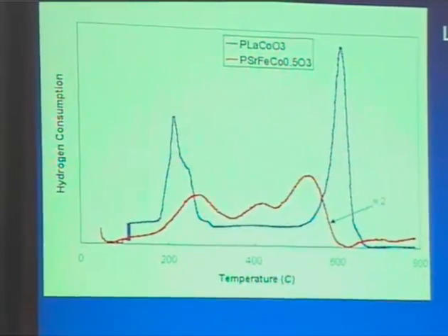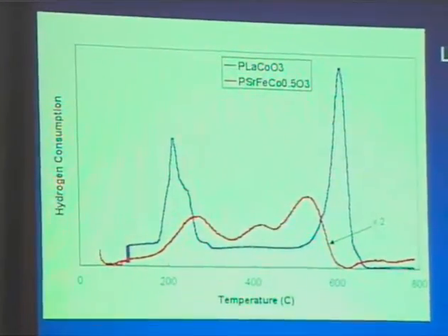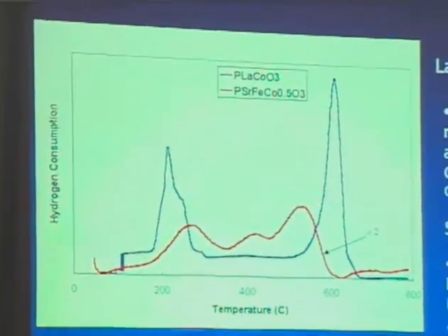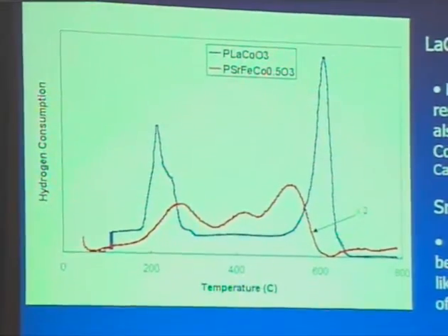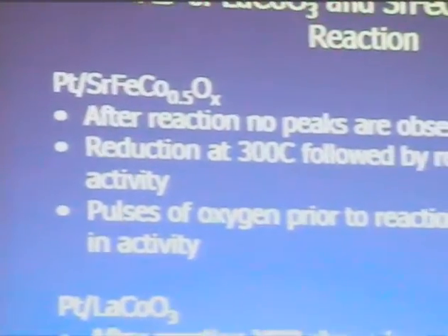With the strontium iron cobalt, we see two reduction peaks after the reduction of the metal, and those are most likely due to the reduction of the support material. When we've done X-ray diffraction on these materials after reaction, for the strontium iron cobalt, we see no diffraction peaks observed at all. So it's a completely amorphous material.